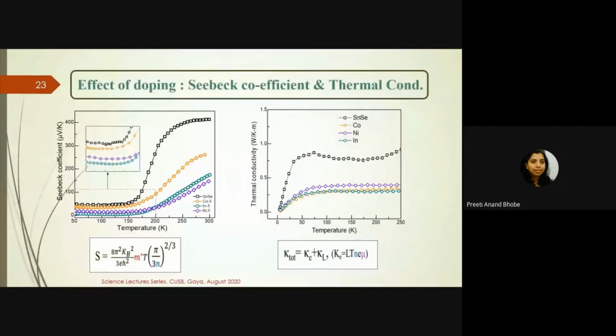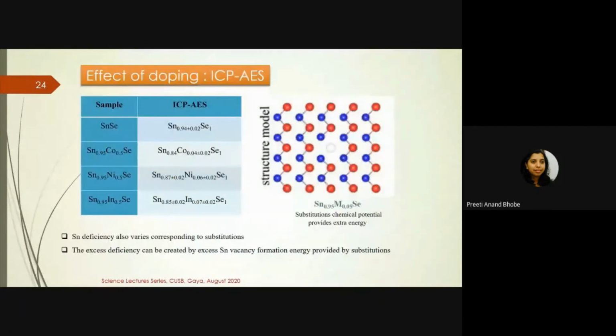So what exactly has happened? How is this doping different from that of copper? Why is there such a drastic difference that we see in these elements? The answer lies in the ICP measurements that one does to find exactly how much indium, how much cobalt, how much Sn, how much Se is there in our composition. And when we do this kind of analysis, we find that we were planning to make SnSe, but SnSe always forms with some deficiency of Sn. It should have been a 1:1 ratio, but what we find is a 0.94:1 ratio. This is generally true for SnSe and is considered one of the reasons for it showing the p-type nature.